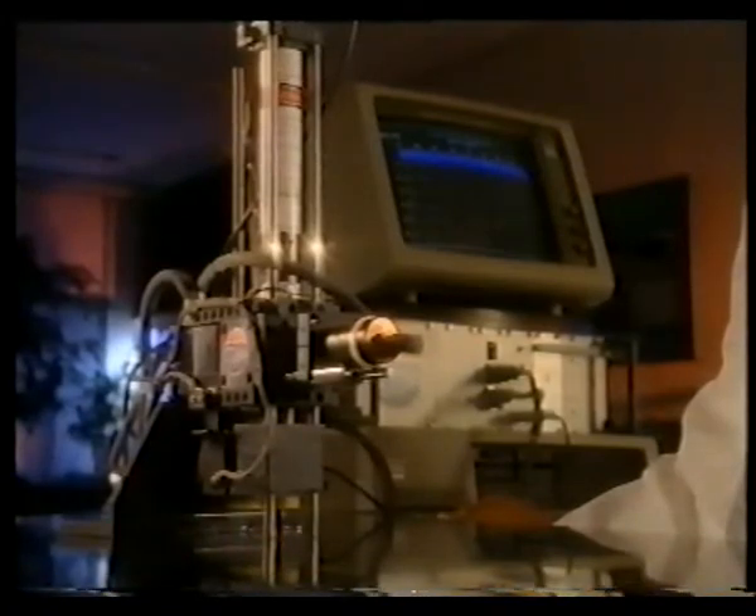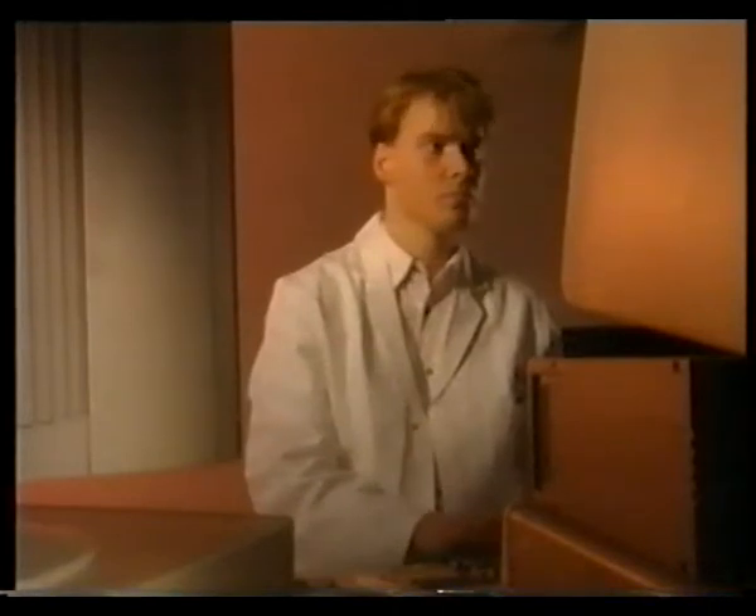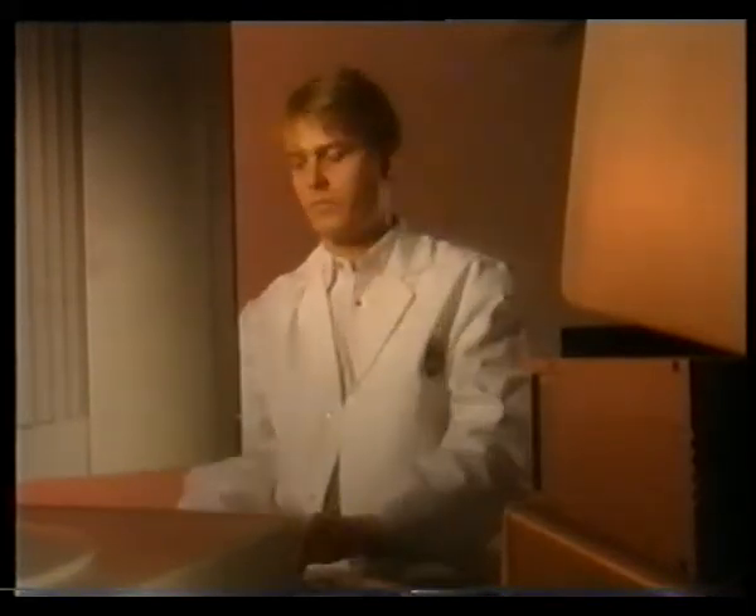By measuring the reflected light, information is gathered about the number of layers, the thickness of each layer, the orientation of each layer, and the presence of inserts. The Fokker STAC tester is controlled by a simple menu-driven computer program. The screen shows the orientation of the fibers and thickness of each layer at every depth level in the laminated structure.